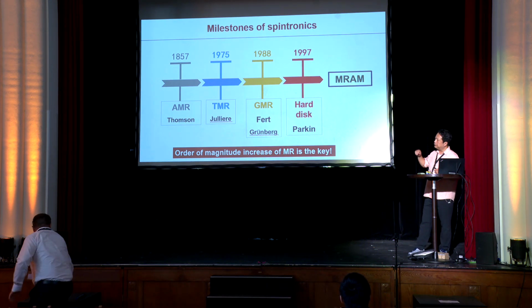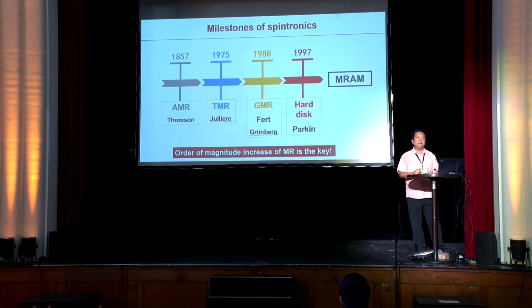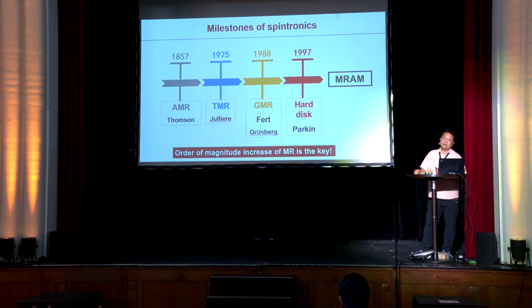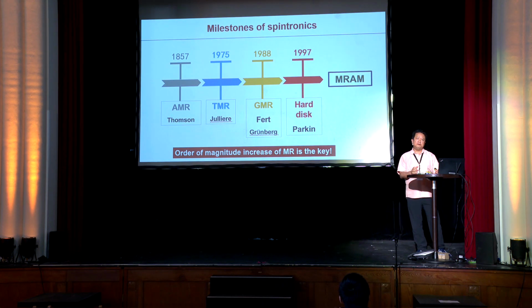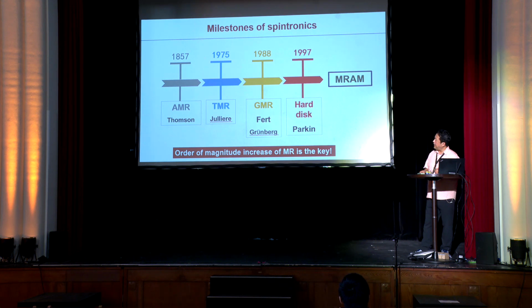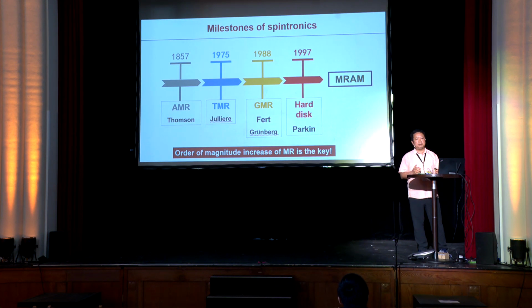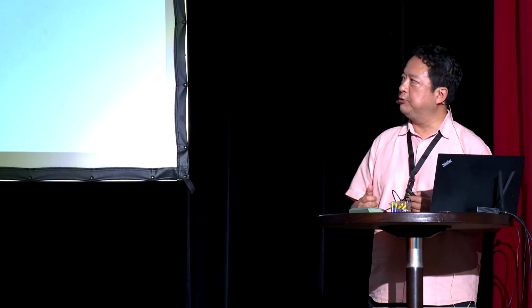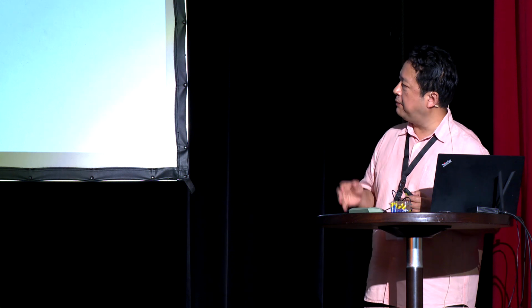Soon people became a bit more ambitious, trying to make this GMR into MRAM. However, the GMR is a bit too small and the resistance is too low for MRAM application. Then there was a revisit of the TMR effect, with first the theory prediction and then the experimental realization. Now these days, you can make a TMR of a few hundred percent at room temperature, so it's large enough for MRAM applications. As a matter of fact, MRAM is already in the market, generating billions of dollars, but there is still room to go to make it a real potential application.